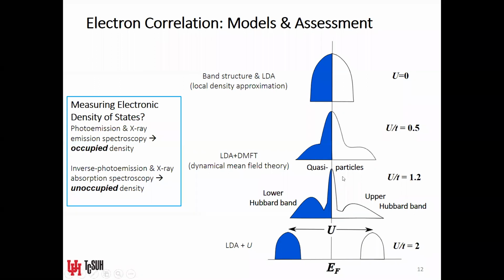Well, I should say that when you see these upper and lower Hubbard bands, these are forming due to the repulsion or the interaction between electrons, okay? You're putting some electrons farther away in the filled states over here in blue, and you're putting density of states farther away. You're pushing the conduction band or the empty states farther away from those filled states. And then in very strong insulating cases, you have these distinct occupied and unoccupied density of states that can be on the order of the Coulombic U value itself.